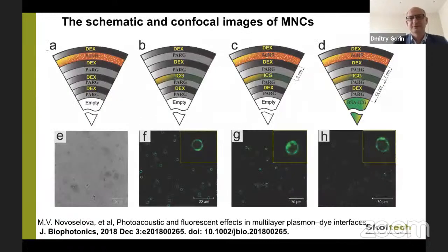And then we apply this idea for preparation of complex structures that have indocyanine green in the shell. Indocyanine green is a fluorescence dye that is widely used in clinical practice, for angiography for example, and it's an FDA-approved dye since, I think, 1960. And you can also see a layer of gold nanorods at a very short distance, and we expected quenching of ICG close to the gold nanorods. Then we have the same structure, but with encapsulated conjugate of albumin with the same dye. And here we have long distances, therefore we expect high fluorescence enhancement from the fluorescence of this conjugate.